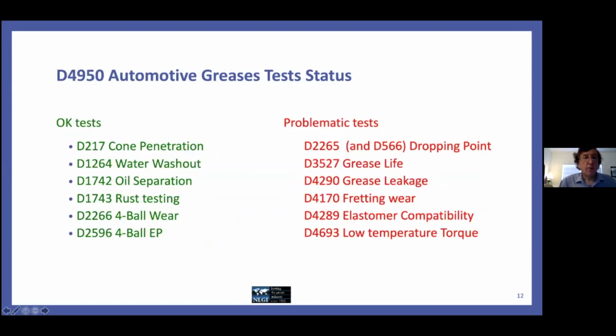So as you can see from this list, we went through in the committee the 12 tests that are covered by the NLGI GCLB specification. And we concluded that the tests listed in green on the left, cone penetration, water washout, oil separation, rust testing, 4-ball wear, 4-ball EP, those test methods all had good repeatability, or as good repeatability and reproducibility as grease test methods have, and there were no issues with hardware and other issues. As to the other tests, there were some problems.